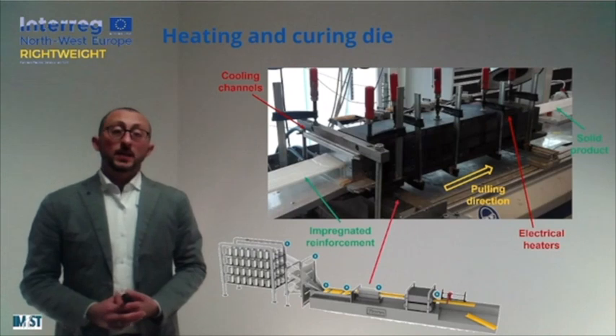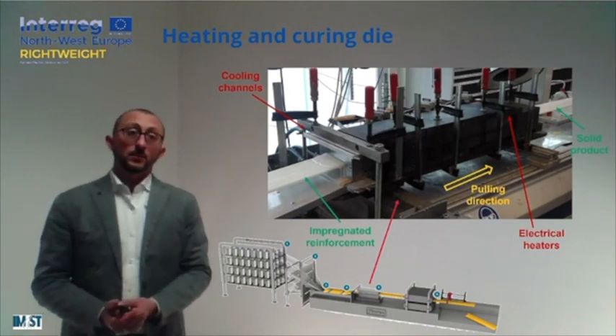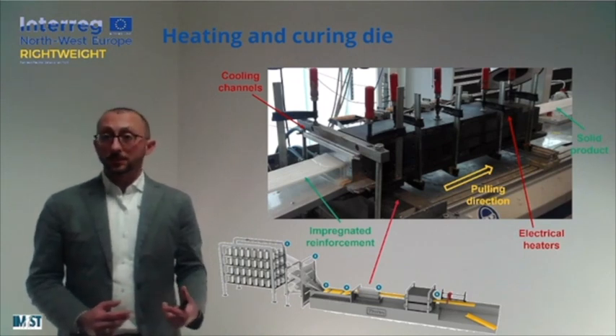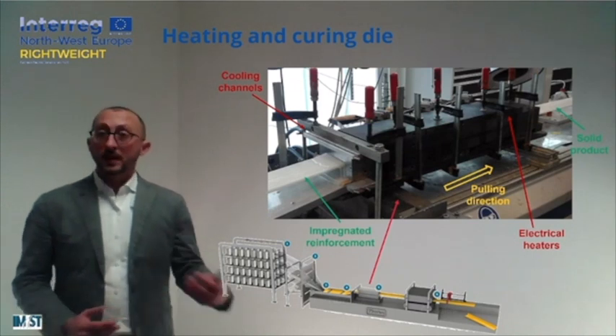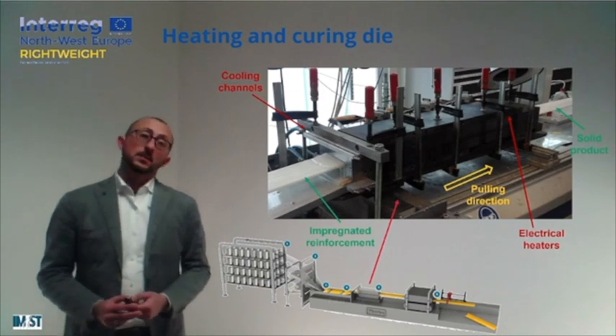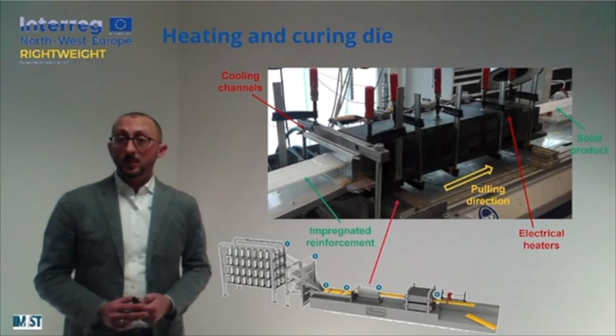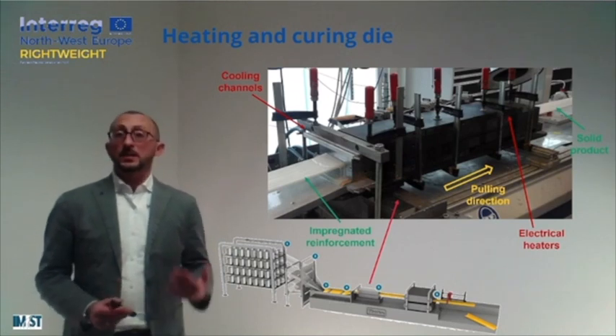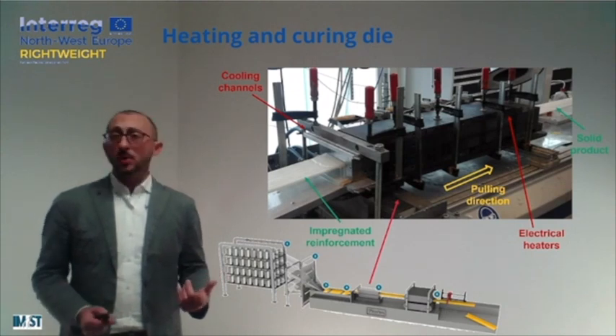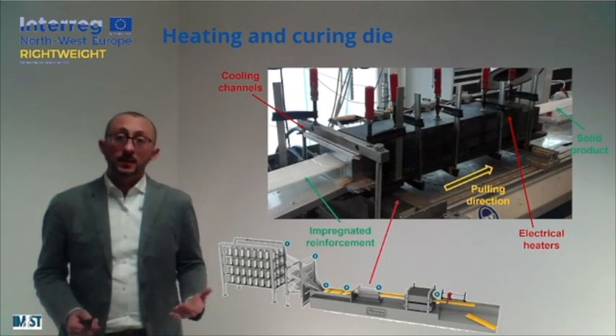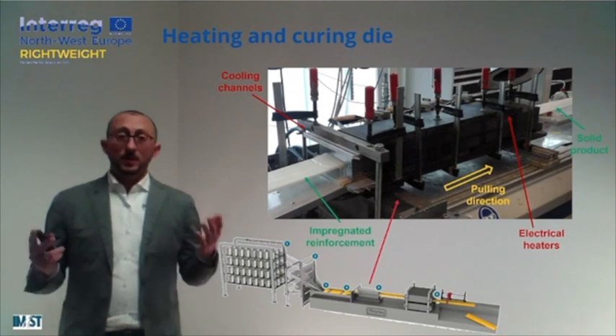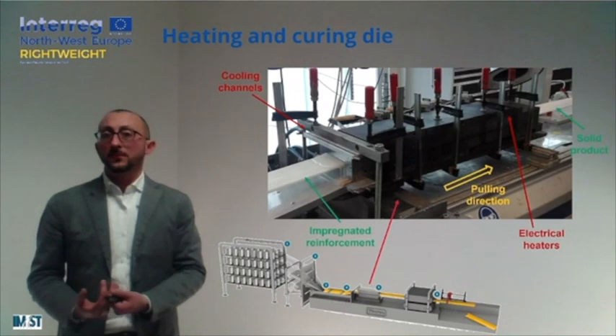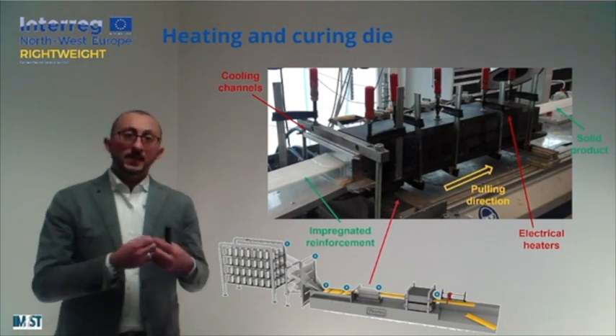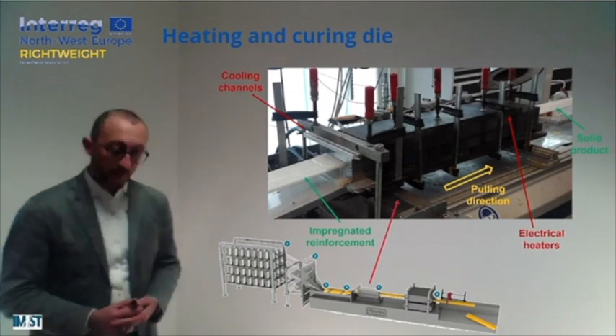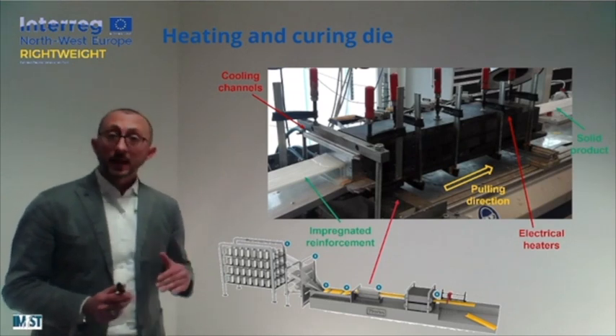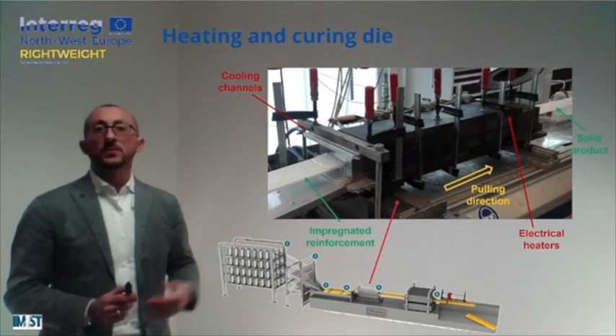increase the durability of the die, generally the surfaces that are in contact with the workpiece are chromium coated in order to have a longer life and produce more meters of our composite product. The die is heated using several systems, such as steam or oil, but the most common one is based for sure on electrical heaters, like plates or cartridges, so just dissipating, using the Joule effect, some heat inside the die, and this heat will be then transferred to the processing material in order to activate the curing reaction and have some cross-linking and increase of the mechanical properties.